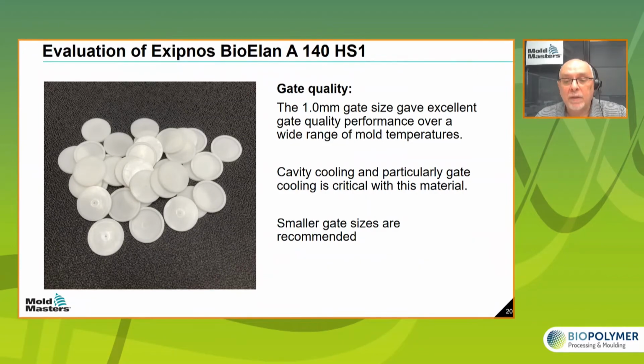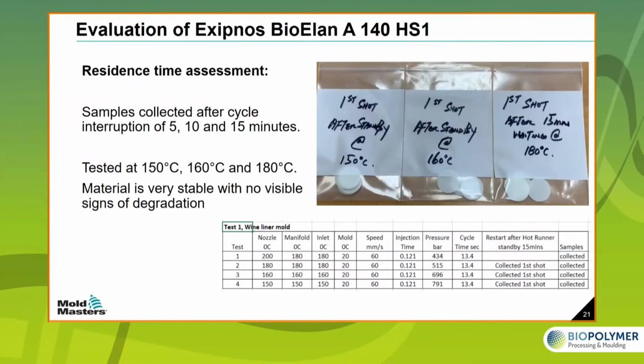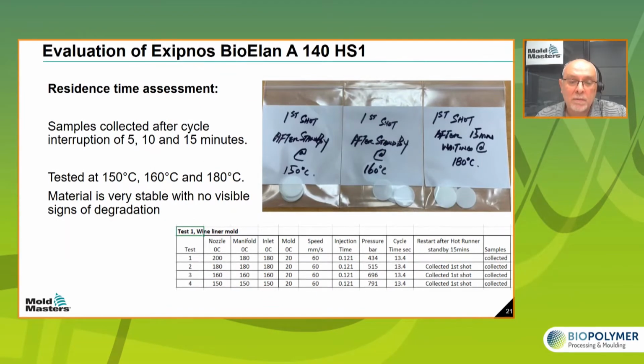We discovered that cavity cooling is important when running this material, and smaller gate sizes are recommended. So this was a 1 millimeter gate size. As part of our residence time assessment, we collected samples after an interruption of 5 minutes, 10 minutes, and 15 minutes, and we tested it over a range of temperatures starting at 150, 160, and 180 degrees. And our finding was that this material was surprisingly stable. We did not see any visible signs of degradation going through this test.